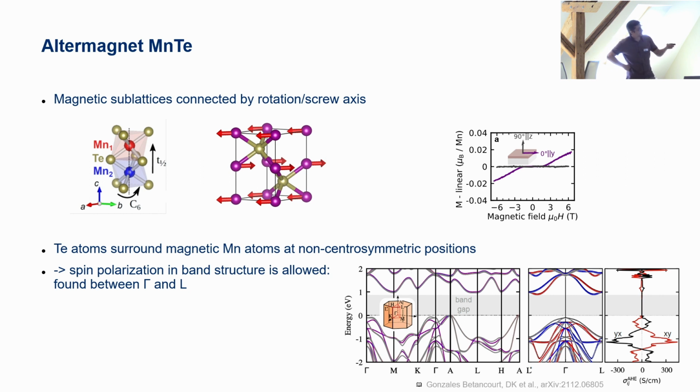And related, you can also obtain, all by first principle calculations done mostly by Raphael, anomalous Hall conductivity, which can be also several hundred Siemens per centimeter when you go far enough away from the valence band edge. As you can see here, we have a band gap. So this is a semiconducting material, which will most likely allow us to combine these sort of spin transport properties in a magnetically ordered system with semiconducting properties.